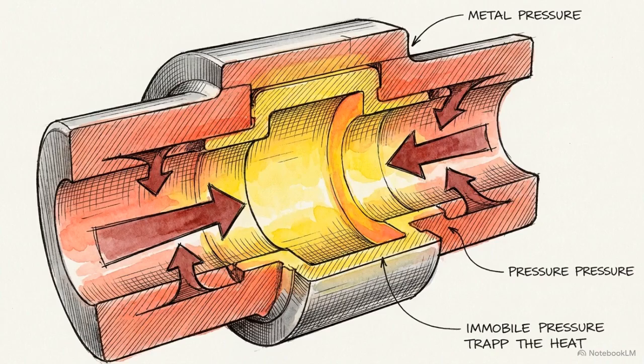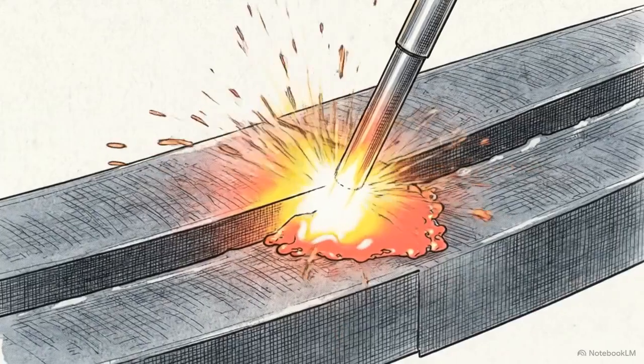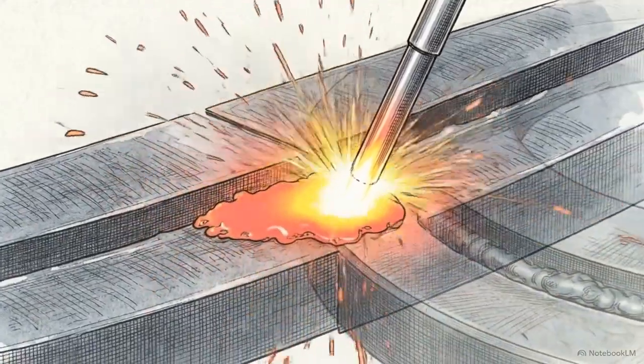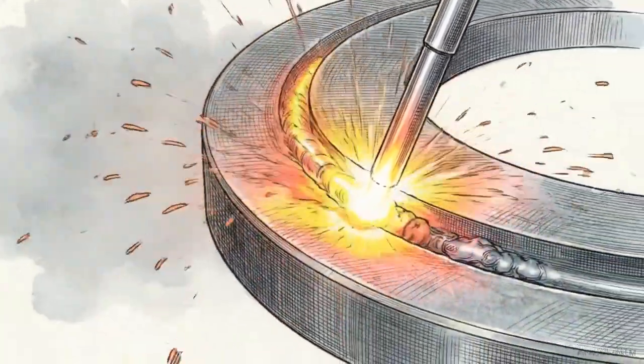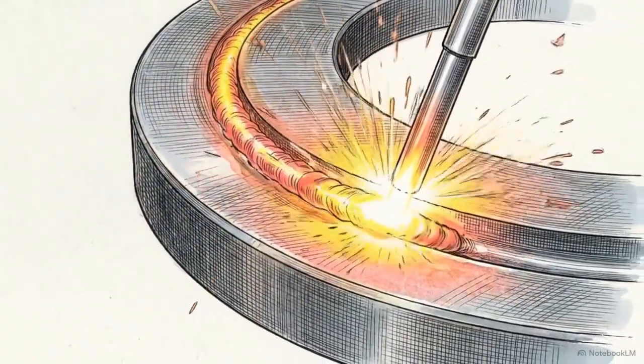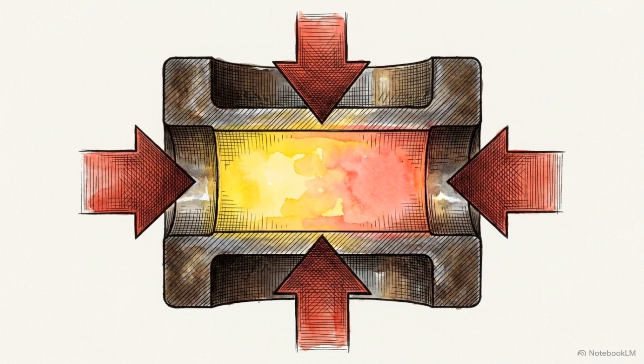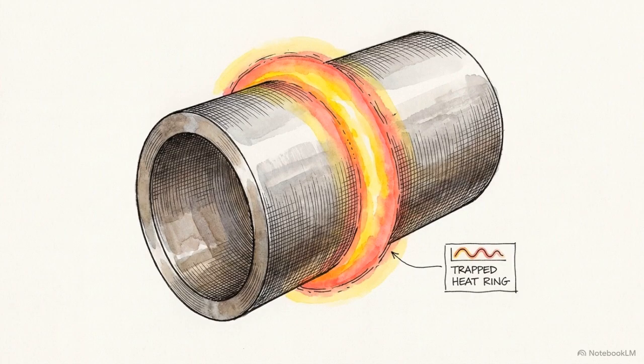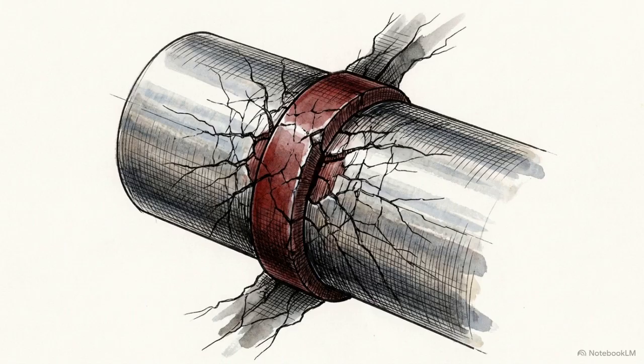Welding residual stresses are locked-in forces generated by the localized thermal expansion and rapid cooling of metal during fabrication. During assembly, a continuous, multi-pass circular weld was carefully applied to fuse the heavy structural shaft components permanently together. The combination of a thick wall profile and that rigid internal backing ring creates extreme geometric restraint. The metal cannot freely expand or contract. Applying a continuous single-segment weld around the circumference traps intense thermal energy. The heat cannot dissipate uniformly, which builds internal shrinkage forces as the molten pool solidifies.